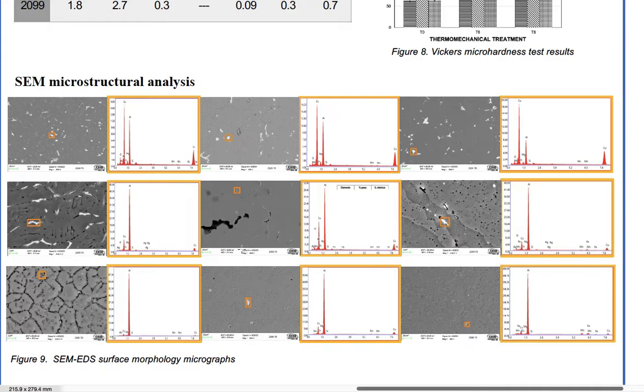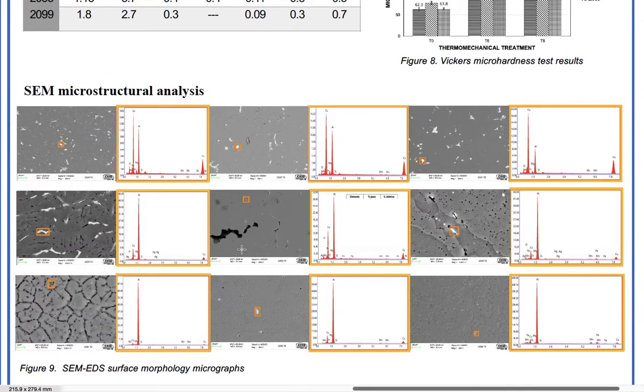The SEM images show, among other things, the large number of precipitates in the 2024 alloys with respect to the other alloys, especially in the T0 and T8 treatments. The high percentage of copper in the precipitates is also observed, above the percentage of aluminum. The 2055 alloy presented cracks generated at the grain boundary. The percentage of copper in the precipitates is lower than in the 2024 alloy.